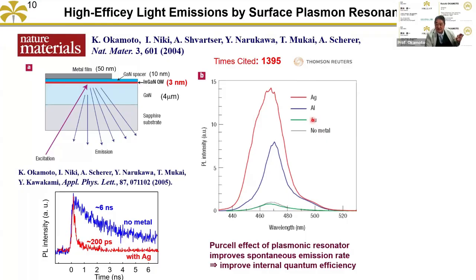At the interface of the silver and the gallium nitride, the surface plasmon is generated in the blue light region. That's why the enhancement is very large. But for the aluminum interface, the surface plasmon resonance is generated in the UV light region. That's why it becomes small. And for the gold interface, the surface plasmon is generated in the red light region, and there is no mode in the blue light region. That's why for the gold surface there is no enhancement. So we found that surface plasmon resonance is useful for highly efficient light emission.